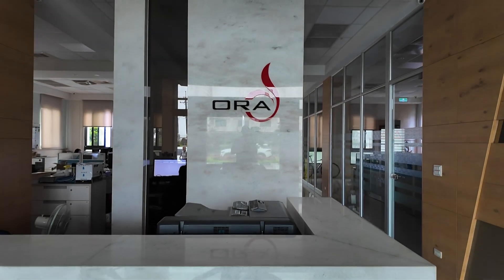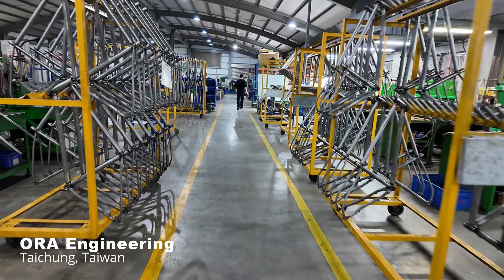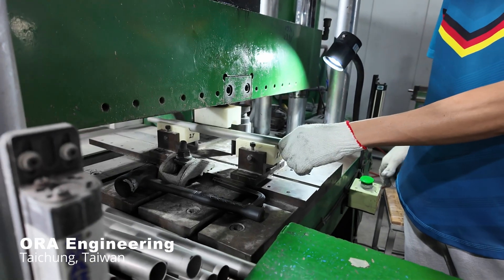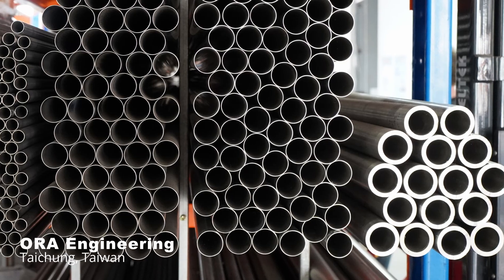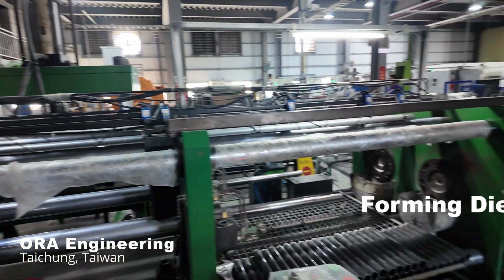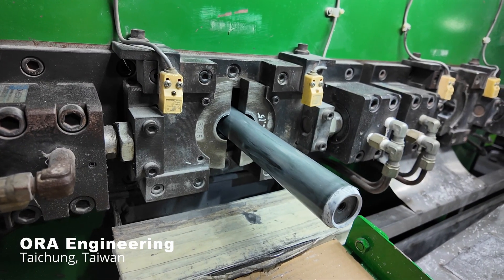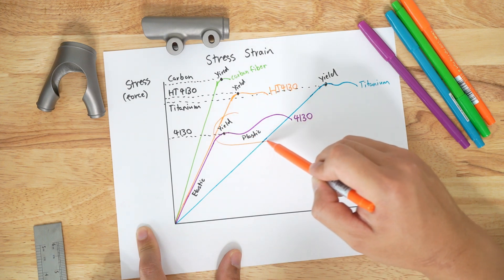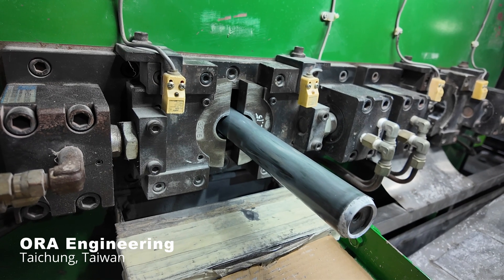The reason why is the highest stress happens where the tubes join. Earlier this year, I visited ORA Engineering in Taiwan where I learned how steel and titanium tubes were made. They first start out as a large and thick seamless mother tube. A hydraulic ram forces the mother tube through a die with an internal mandrel to form the inner and outer diameters. This process is known as butting. Butting cold works, plastically deforms, the material making it stronger. It is repeated multiple times to form the final geometry of the tube.